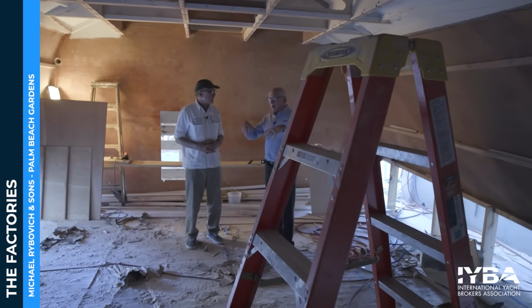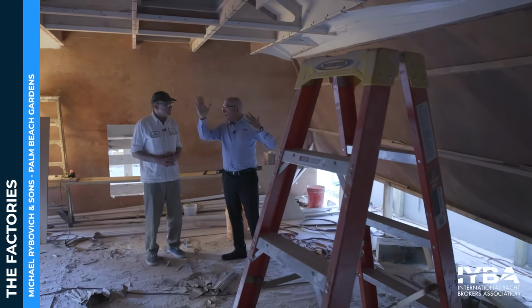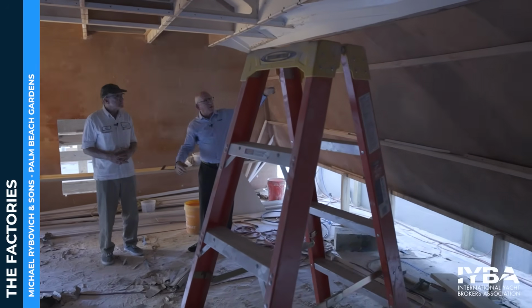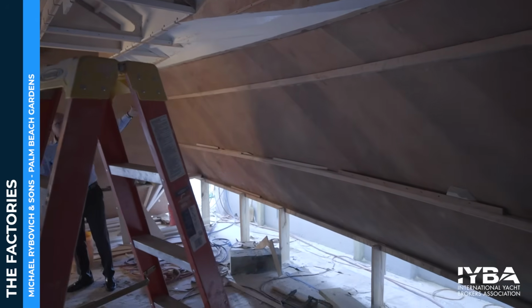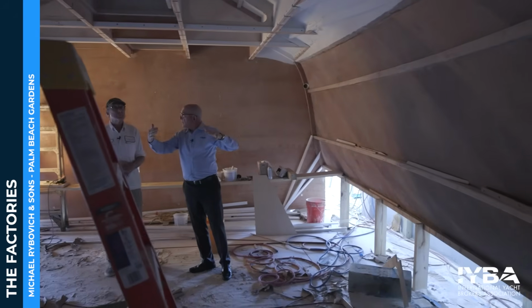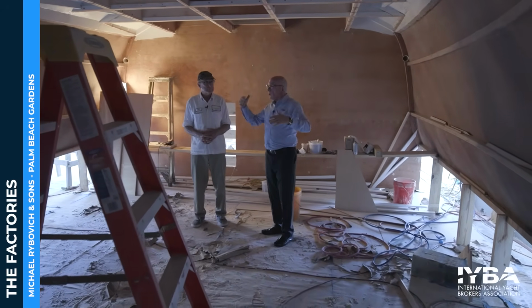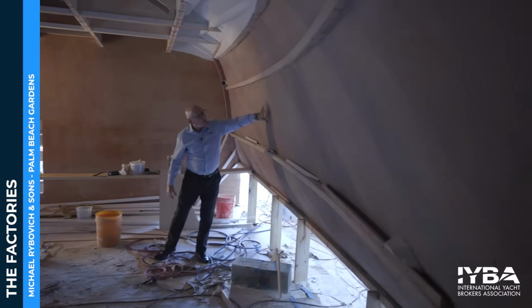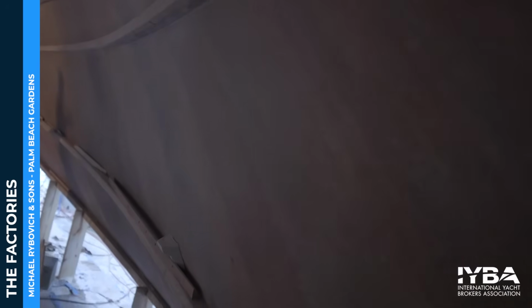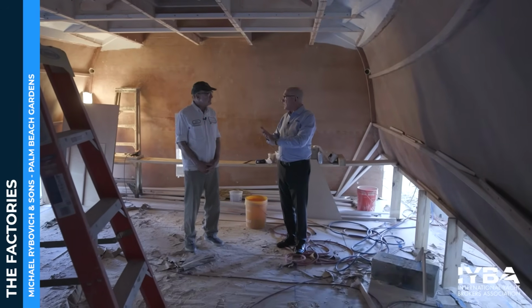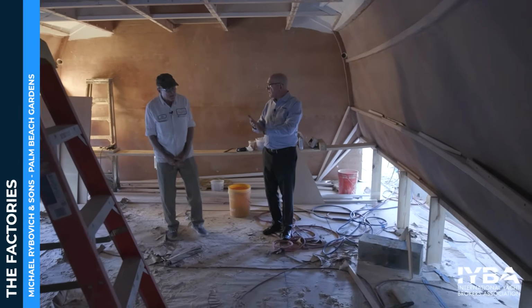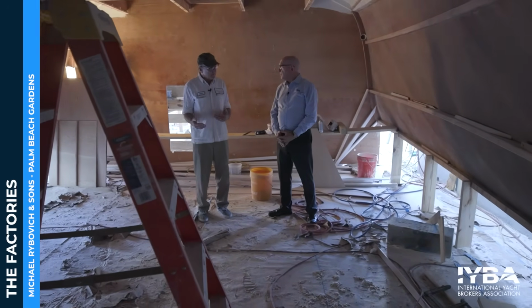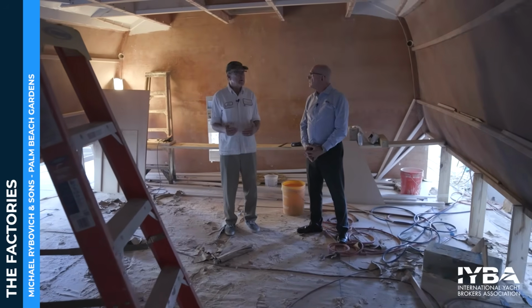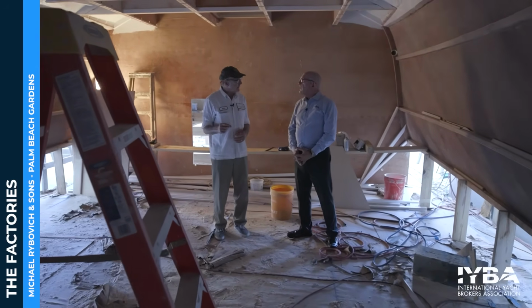So prior to the process where we are right now, there would have been a jig or a plywood bulkhead here. That is correct. And there would be notches cut out of that bulkhead where the keel, the chines, and the stringers would be, which give you your structural integrity. And then across them at a diagonal, as you can see in the planking here, you put your first layer on and it's affixed to the structural members. And then your next layer goes on and it starts to give you some rigidity. And then your third layer goes on, so 3 layers of 5/16 gives you 1/16 inch short of a full inch of hull thickness. Actually, it's about an inch because of the thickness in the glue. Okay. And then we glass that inside and out. The total thickness usually ends up about 1 1/8 inches with fiberglass on both sides.